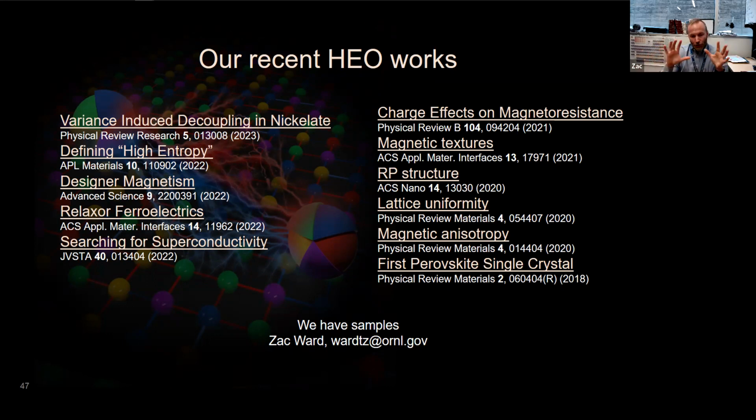What we saw was that structurally, this thing is unexpectedly uniform. It picks a slightly orthorhombic distortion type throughout the entire thing. As far as we can tell with lots of X-ray diffraction, there are not local pockets of one distortion type or another. It's really very uniform. If you want to get these canted states, often that's tied into a change in the Jahn-Teller distortion or some kind of a tilt or something else that plays with the orbital. So in this case at least, it looks like the crystal structure is uniform. Whatever's happening there is uniform throughout.